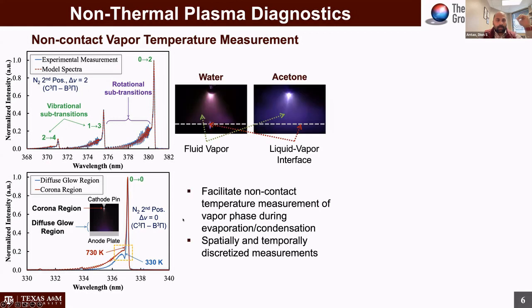When I was doing my postdoc, I got thinking about doing non-contact temperature measurements above the liquid-vapor interface. And so what we're attempting to do in this aspect of this project essentially is to do non-contact temperature measurements above a liquid-vapor interface during evaporation or during condensation. And we have the ability to do it in a spatially discretized manner as well as in a transient manner. We are currently building the test setup for these tests at the moment.